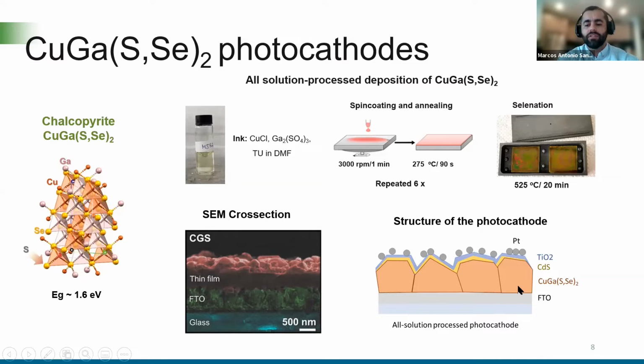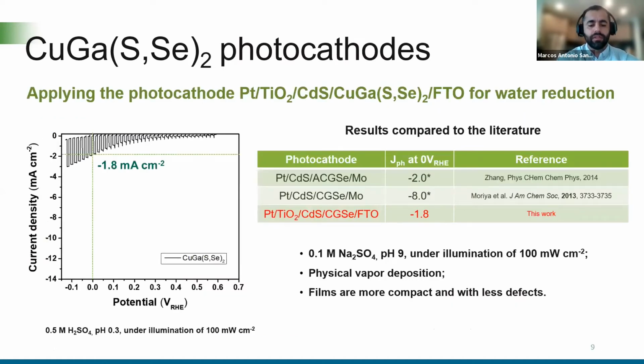And we finished the device by, after that, depositing a buffer layer of about 40 nanometers of cadmium sulfide, and then 100 nanometers of titanium dioxide, which acts as an electron transport layer and also as a protective layer, increasing the stability of the photocathode. And we finished the fabrication of the device by doing the deposition of platinum as a cocatalyst. This copper gallium sulfoselenide photocathode produces a photocurrent of 1.8 milliamperes per square centimeter, which is lower than the values obtained for the ones fabricated by vacuum-based methods on molybdenum substrates.